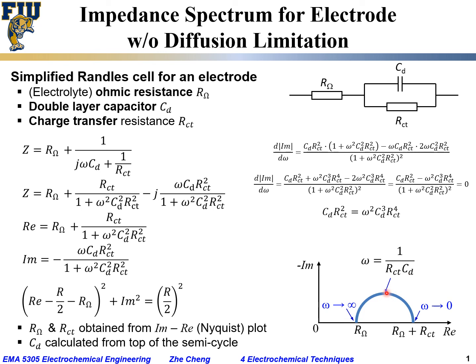measurement. So again, this slide shows how we can measure the impedance spectrum for a single electrode, and then based on that single electrode impedance spectrum, assuming no diffusion limitation, the mass transfer is very fast, from that we can get three pieces of information. One is the ohmic resistance associated with the electrolyte near that electrode, then that electrode's charge transfer resistance, and then also for that electrode-electrolyte interface, the double layer capacitance. Okay, we can get three important parameters related to kinetics for the electrode reaction of interest.